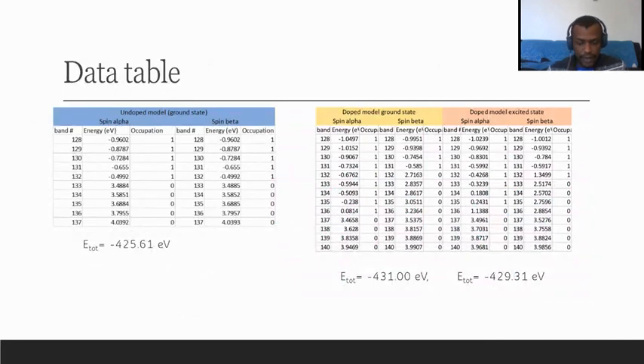So here in the data table, after geometry optimization, the total energy of the undoped model, which is shown at the left, is minus 425, and then the other two total energies after geometry optimization were also included for the doped model, and then the doped model after being excited. So in the first data table, we can see the energies of the bands are the same, and the occupations are also the same, which would translate into very similar density of states plots that we will see next.